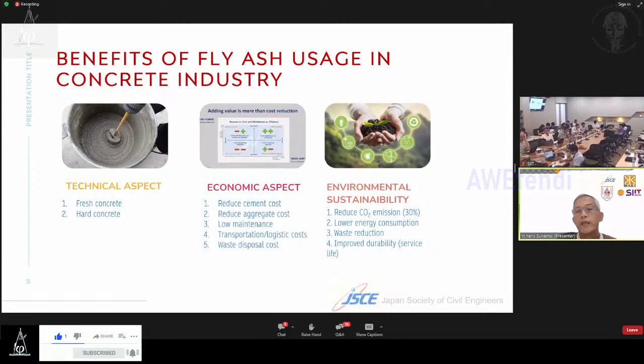Next aspect is the environmental sustainability. Fly ash use can reduce carbon dioxide emission because the main component of concrete is cement. And we know that cement production contributes about 6 to 7% of the total carbon dioxide emission into the atmosphere. So by reducing cement consumption, we help reduce carbon dioxide emission. According to some data sources, the use of fly ash in concrete can reduce carbon dioxide emission by about 30% from before.